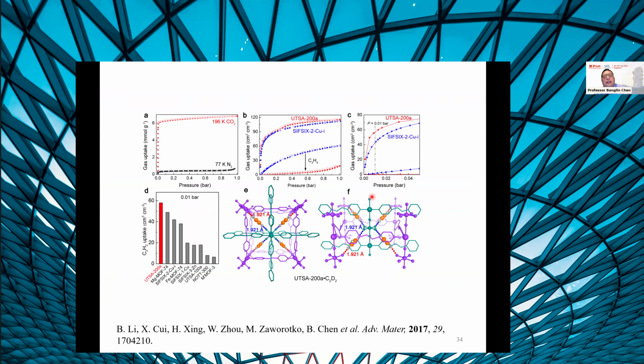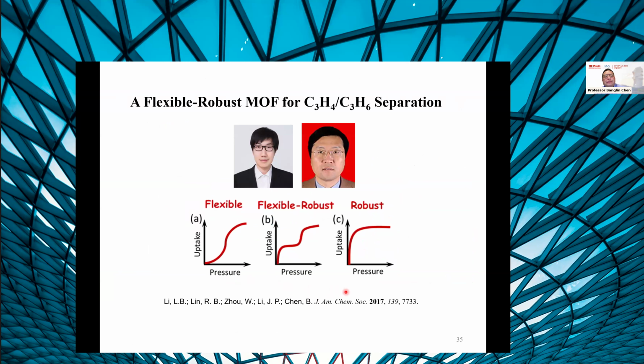So now you will see that the acetylene uptake does not change much, but the ethylene uptake is significantly reduced. So the purity and the productivity of the product we can maximize. So this is another very powerful example indicating how, with reticular chemistry, we can tune the separation performance.